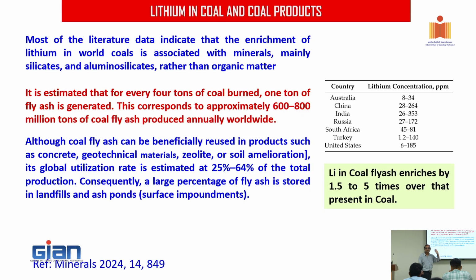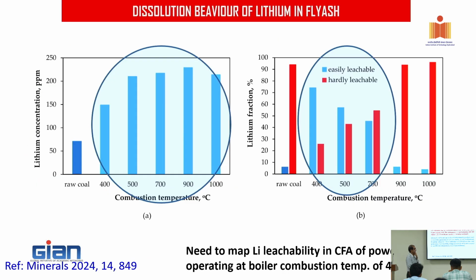But there is a catch here. Can we recover this lithium from the coal fly ash? Yes, but there is a condition. What is that? They found that lithium recovery is better only when the fly ash is collected from those boilers which operate at temperatures less than 800-900 degrees centigrade. If the temperature is more, lithium gets into the refractory form, that is mullite and all those glassy phases. So leachability will be very difficult. So the boiler temperature is very important for seeing the feasibility of recovery of lithium from coal fly ash.